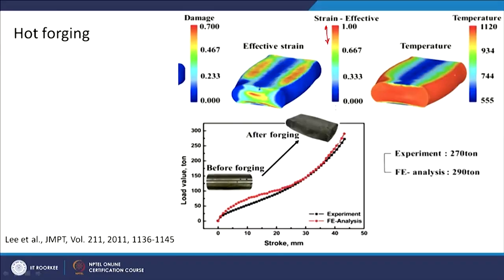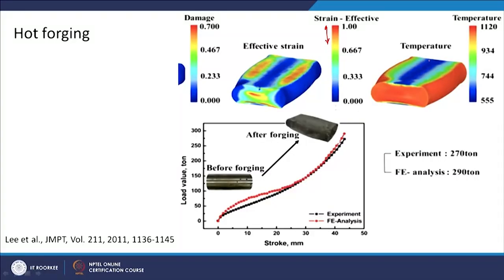Also, you can see that there is a temperature profile here. So the rest of the billet, as you can see, is still at a high temperature, around 1120 degrees Celsius. And the blue color is where the ram comes in contact with the billet. Because the ram must be at low temperature compared to the billet, a lot of heat must have been dissipated from there. That is why you see this low temperature region on the top. So that also we have to account for, that there can be temperature variation in the same material, strain variation, strain rate variation.